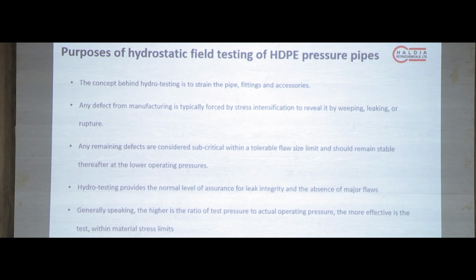Generally speaking, the higher the ratio of test pressure to actual operating pressure, the more effective is the test within the material stress limits. That means if the pipe is tested at a higher pressure and the actual pressure during the service life is much lower compared to that, then the product quality is more assured during the service life. The chances of failure will be minimum.